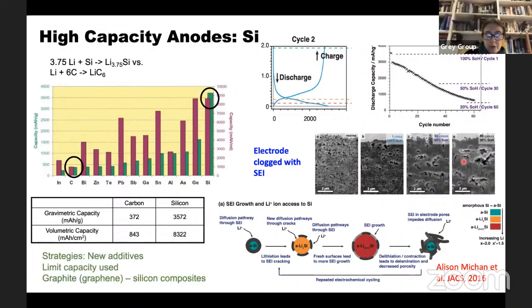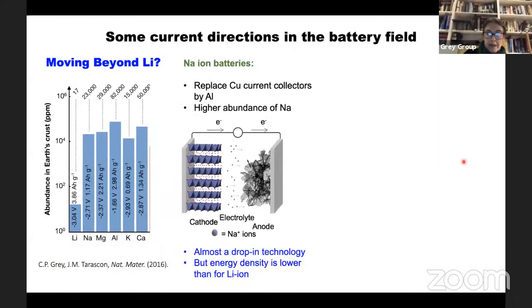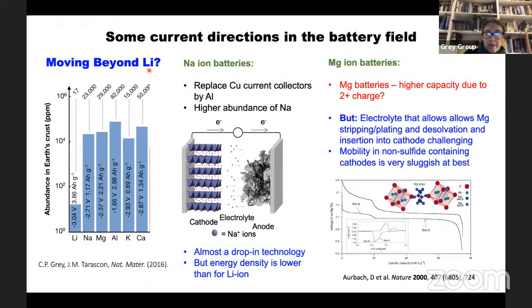So what we did was to come up, well, we've been thinking about new strategies to overcome that, but this is still a challenge, even though Tesla is starting to put a bit of silicon in their cars. So let's think about, where do we go next? And an obvious place to move beyond lithium is to move to sodium. So it's almost a drop-in technology, but sodium is bigger than lithium. So as a result, the energy density is lower. And even more surprisingly, or maybe not, sodium you can't intercalate into graphite. You can intercalate lithium, you can intercalate potassium, but sodium is just the wrong size. And so instead we have to think about new anode materials. And this is an example of a disordered carbon that will react.